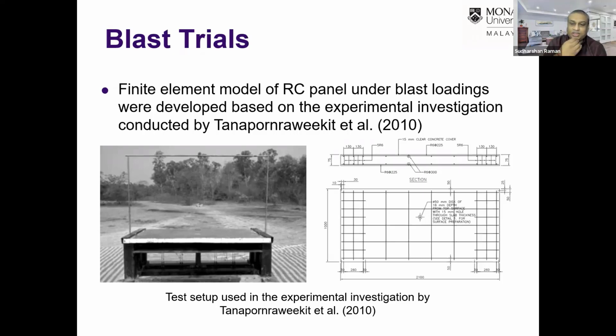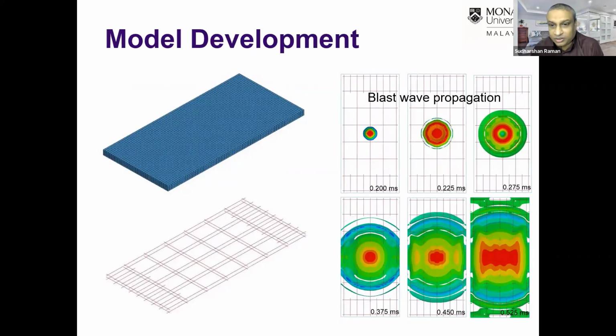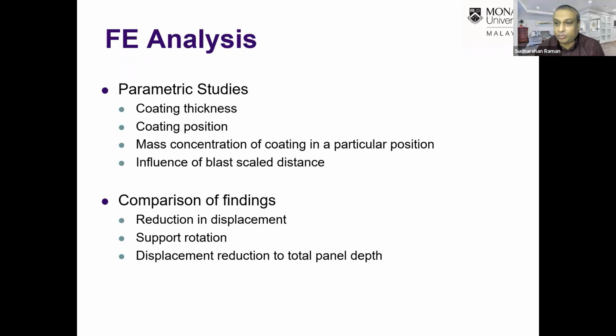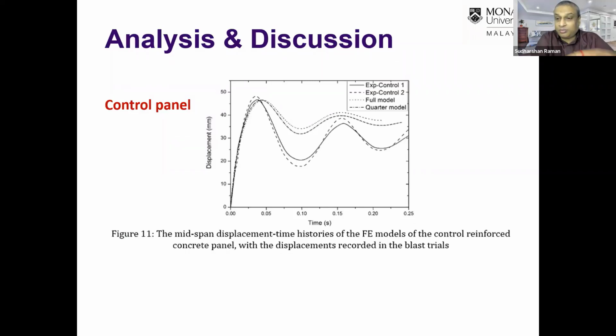So what we have done is we have taken the data from these experiments and the bare concrete data. So this is the model development, the blast wave parameters, blast wave propagation. This diagram shows the blast wave propagation and how we developed the finite element models. And then we undertook parametric studies by varying the coating thickness. We modeled the bare panel and then we applied the coating. What we varied was the coating thickness, coating position, mass concentration of coating at a particular position, and the influence of blast scaled distance. And then we compared the findings of reduction in displacement, support rotation, as well as displacement reduction to the total depth. So I will present part of the data here.